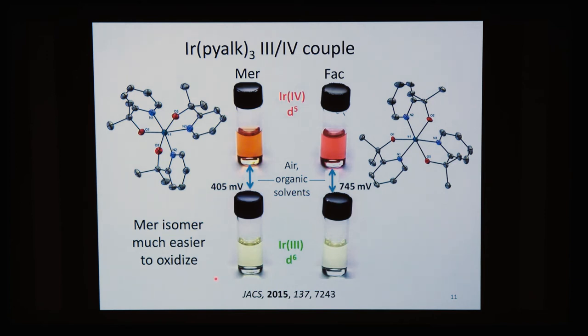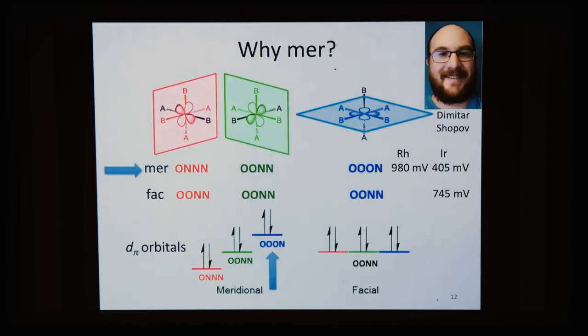And there is a big difference between the meridional isomer and the facial isomer, 350 millivolts difference in the oxidation potential. And it was Dimitar who proposed the explanation, because if all the anionic donor ligands are in the same plane, the blue plane in this case, then the DXY orbital in the blue plane is going to be destabilized under crystal field theory. And we will have the situation as shown by the arrow here, in which the electrons are raised in energy, making it easier to remove one or, in fact, even two, as we see later.